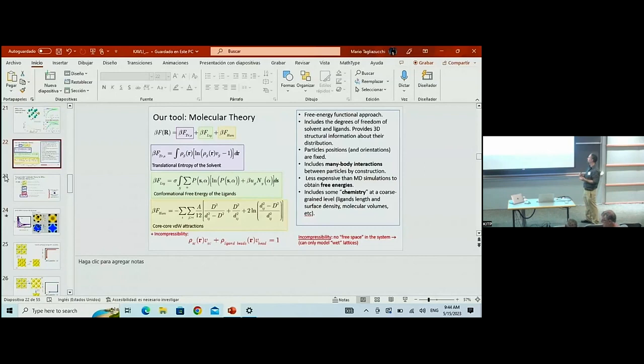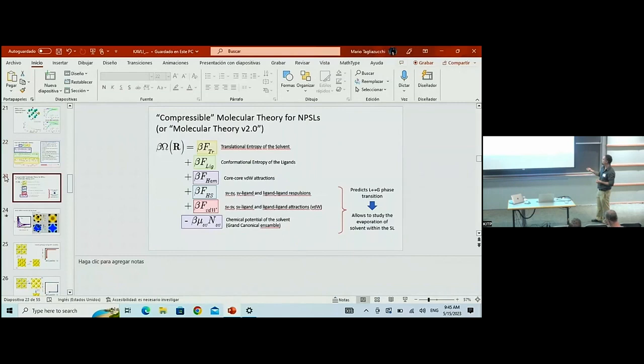Also, because we are modeling hydrocarbons, we include this term here. This one is just the Gibbs entropy equation, and this other contribution over here is an enthalpic contribution from the gauche-trans energy of hydrocarbons. Even though that's a parameter, the gauche-trans energy is something that is known from experiments. And then you have the Hamaker constant of the inorganic cores, and in this other theory you also have some Lennard-Jones parameter for the van der Waals interaction. Most of this information is very straightforward to get from experiments. In this particular theory, we're still trying to fix a few parameters.